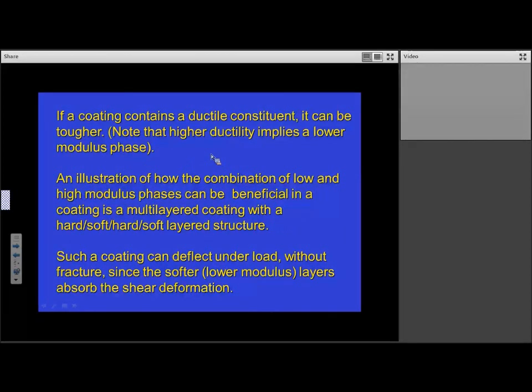So if a coating contains a ductile constituent, it can be tougher. An illustration of how the combination of low and high modulus phases can be beneficial in a coating would be a multi-layered coating with a hard, soft layered structure. Such a coating can deflect under load without fracture, since the softer, lower modulus layers absorb the shear deformation.